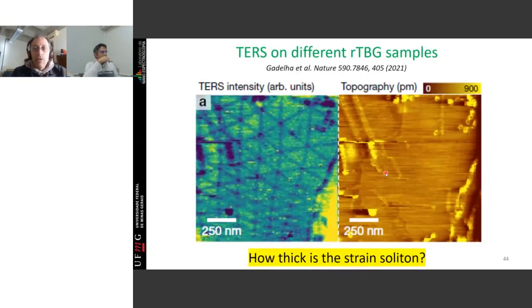And this is what you have on this picture, okay? What you see here in this brownish color is an atomic force microscopy image, so it's the topography. In the topography, what you see is basically junk, okay? You see all this dust, all this stuff. This junk also shows up here. This is the optical spectra. This is the nano-optical spectra. And in the nano-optical spectra, you see the formation of these strain solitons or these domain walls between AB and BA stacked regions. So you cannot see this in topography, but you can see it on the optical spectrum, okay?